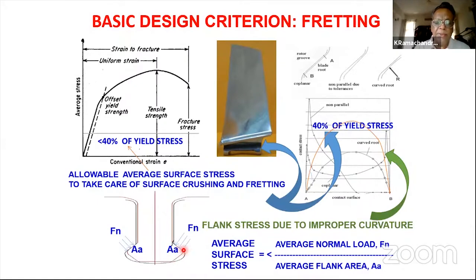And this is bad news because the surfaces are actually gently rubbing. They're in sliding velocity and very high contact Hertz stress there. And this results in local fatigue failure, fretting fatigue failure initiated. And then it goes into a full-scale low cycle fatigue or high cycle fatigue mode of failure.